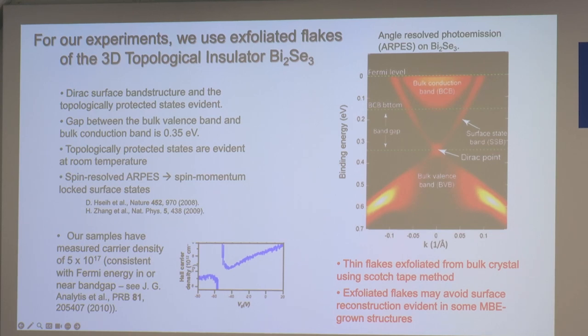You can see, they're very controllable, they're beautiful systems, but for something where you want a really good proximity coupling at the interface, or at least to control it really well, it's sometimes, ironically, harder to do with MBE, because even though it looks really pretty, chemically at the interface, it's not clear what's happening. So in our case, we have exfoliated flakes and just plop them down directly on the magnetic material, and then we know exactly what's at the interface, usually a little bit of dirt and some coupling. Okay? So at least we know what we have there. There's no other layers in between there.